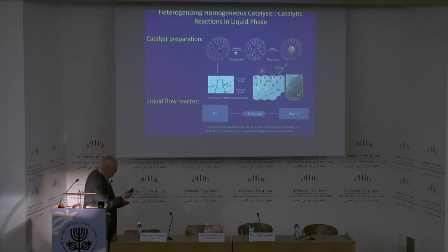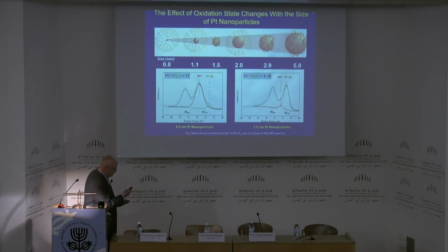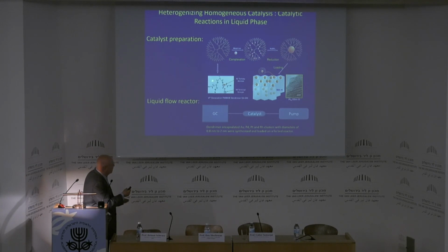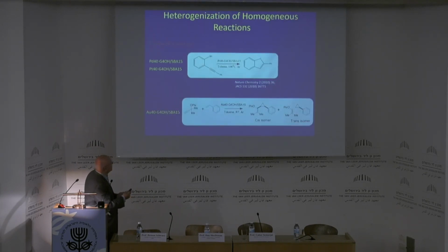We took a support like this dendrimer support, which is sort of like a branch of a tree, and you can put platinum or any metal on it and any size, but the high oxidation metals are the small ones. Then you put it into a support, like a silica support, and run the reactions. What you find is that you can get homogeneous catalytic reactions, and we have 13 papers to show that we can take the 40 atom palladium, platinum, gold, and other transition metals to carry out homogeneous catalytic reactions.